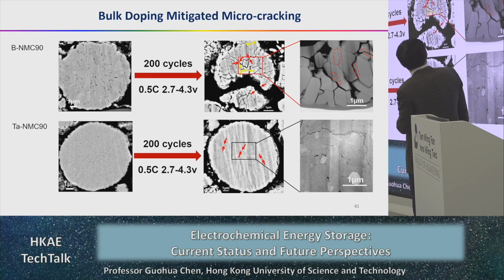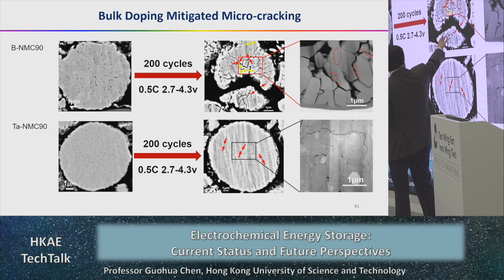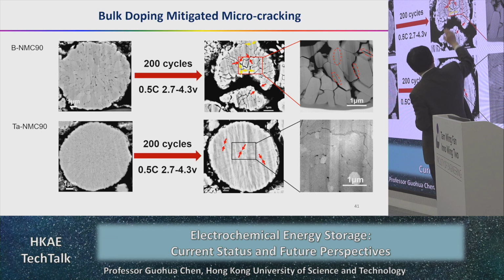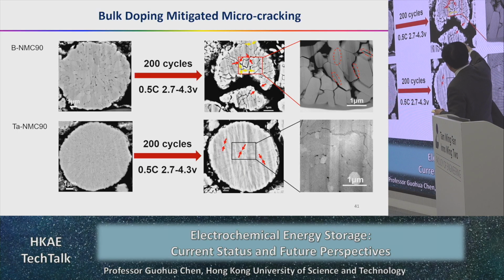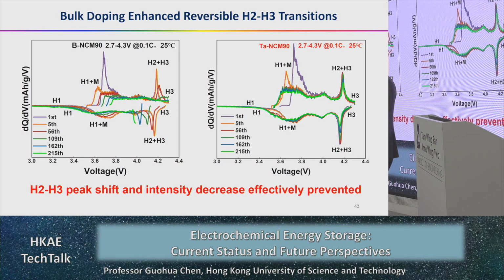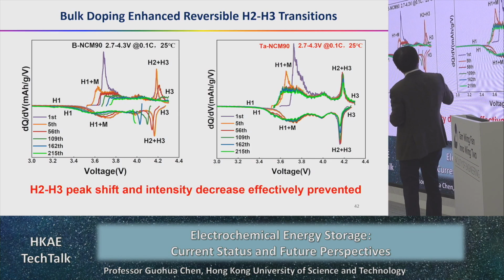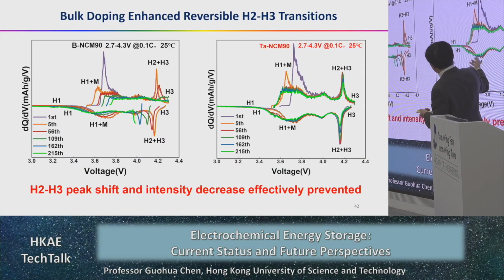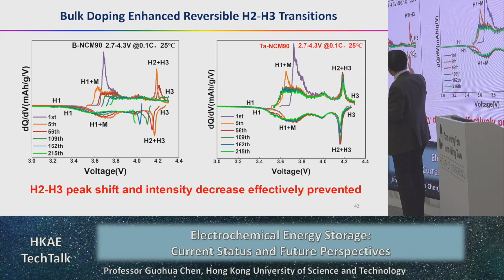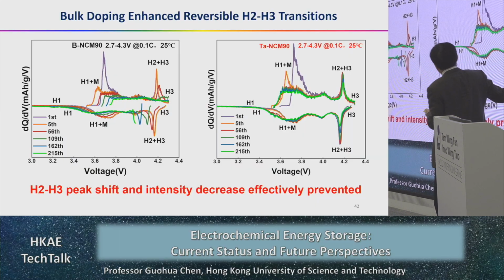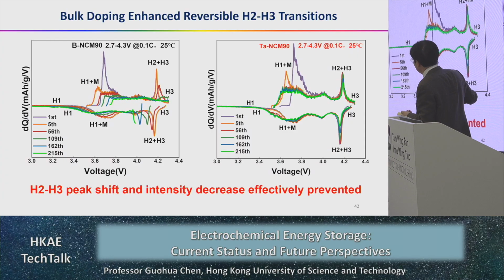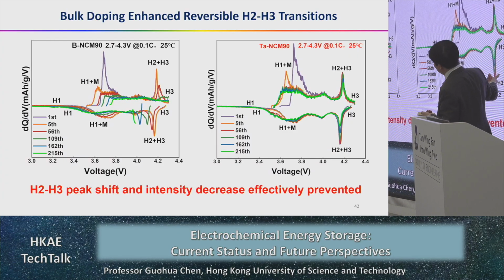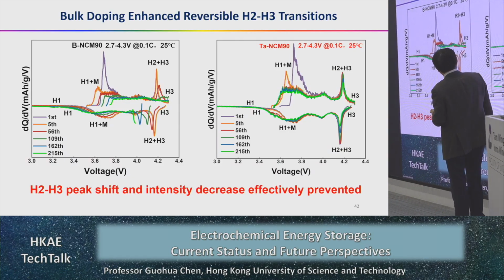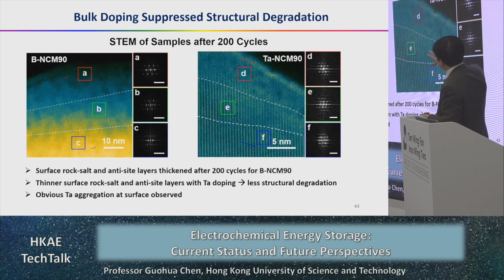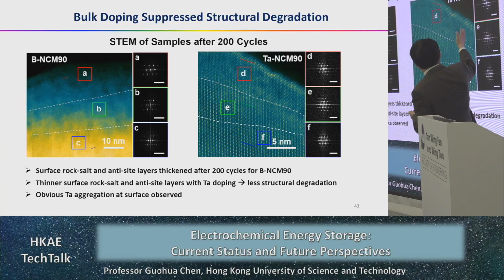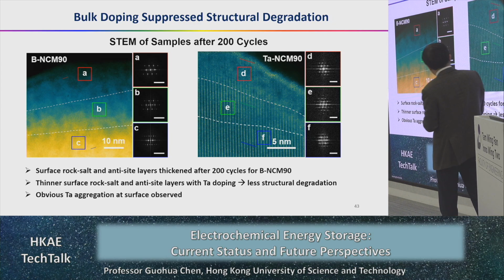And this is further looking at how it can mitigate the bulk structure. This one is without, this is with, so the cracking is significantly suppressed. And this is a more detailed study. The doping can also improve the electrochemical performance. So this H2-H3 peak shift is more reversible, and this one you can see is not that reversible. And this is a further STEM sample looking at what is the change of the structure morphology.